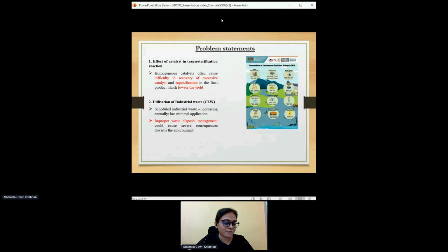Based on the literature review, we discovered there are two main problems. Firstly is the effect of the catalyst in a transesterification reaction, where a homogeneous catalyst is difficult to remove from the reaction mixture because it is present in the same phase, whereas with a base catalyst, when we use a high acid value oil to produce biodiesel, it may cause a saponification process, which will reduce the production yield.